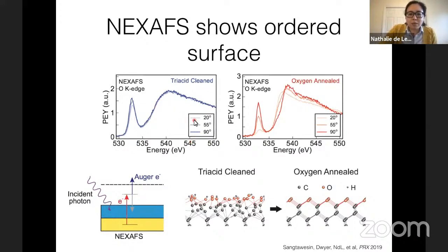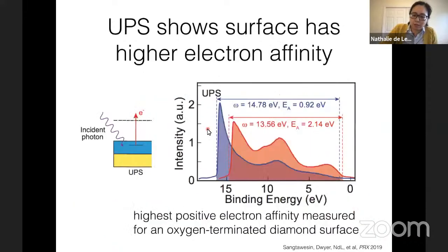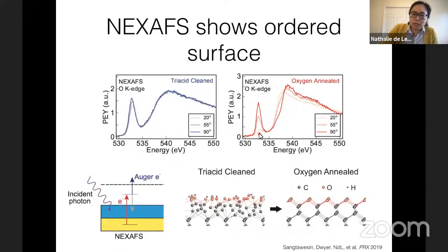But instead, what we can see is that if you, for example, change the polarization of the incident X-rays by tilting your sample, in this acid clean surface, we see very little polarization dependence. Whereas in the oxygen annealed sample, we see this really dramatic polarization dependence. So what this really points to is that these surfaces are somewhat chemically similar, but the acid clean surface is highly disordered, whereas the oxygen annealed surface has these atomically ordered bonds because that allows you to see this polarization contrast.